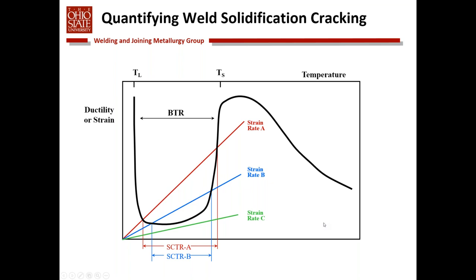So preventing solidification cracking means that we either decrease the strain through how we make the weld and how it's strained during the welding process and during cooling, or we manipulate the ductility curve, making the brittle temperature range number one higher or narrower. And so an approach from the standpoint of alloy development or filler metal development is to try to minimize and manipulate the BTR through composition control.